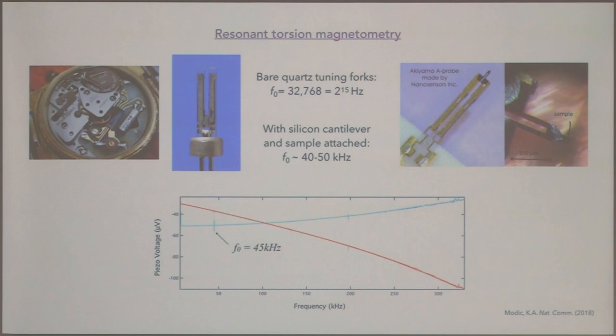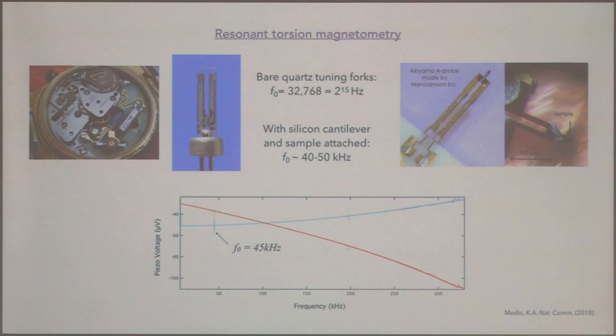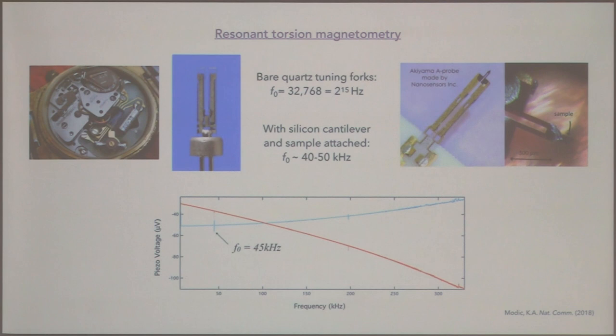What I did was measure magnetic torque and look at scaling, as suggested in a talk the previous day. But there are a lot of issues. We had done this for lithium iridate initially, and you run into many issues doing magnetic torque in very high magnetic fields. Normally you measure a bending amplitude in magnetic field, but that environment is quite harsh. When you get bursts of energy into the magnet, there's a lot of noise and you couple to that in an amplitude measurement. Those bending levers also don't give you the same response whether they bend up or bend down — you have an asymmetrical response and a magnetoresistive contribution.